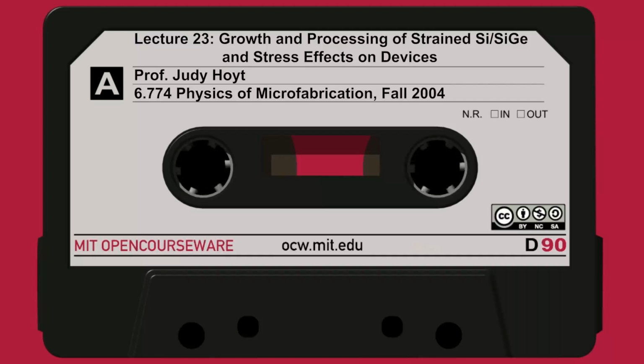Now, if you make it thick enough, eventually there's too much stored energy in those stretched bonds, and the bonds will start breaking. You'll get dislocations, and it'll relax back to its cubic structure. But for thin layers, you can achieve this sort of pseudomorphic structure. You can also do the opposite, or the upside-down experiment. You take a wafer of silicon germanium that's very thick, that's already relaxed, that has a larger lattice parameter, and you try to grow silicon on it by epitaxial growth.